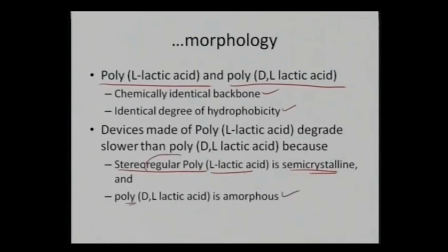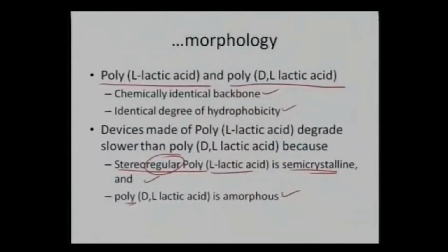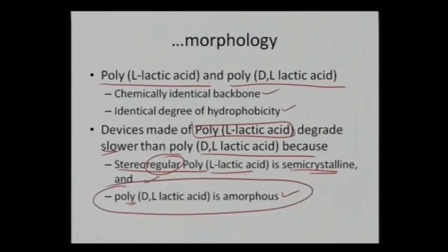So in this case we can see stereoregular poly L-lactic acid is much more semi-crystalline, and since it has much more crystalline regimes, it degrades at a much slower rate. Devices made of poly L-lactic acid will degrade at a much slower rate than poly DL-lactic acid, because poly DL-lactic acid is amorphous in nature.